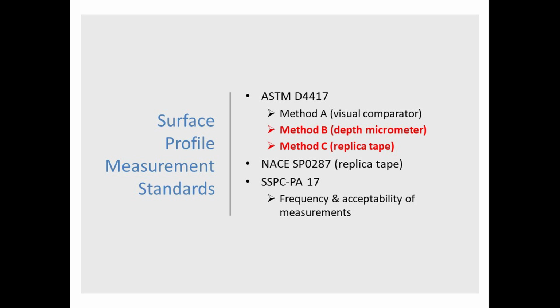NACE also has a standard, SP0287, which is the same as method C in the ASTM standards, the replica method. And then SSPC PA 17 doesn't talk about how to measure surface profile. What it focuses on is how many areas you check. So if I have blast at the inside of this tank car, am I supposed to check 1 area, 50 areas, 3 areas? What am I supposed to check? PA 17 gives us some guidance there. That's a relatively new standard, by the way. It's probably been out about 6 or 7 years.